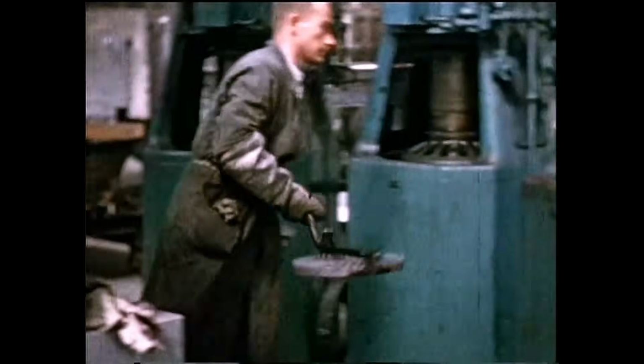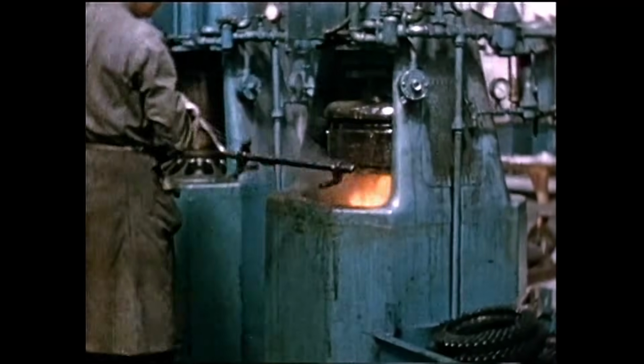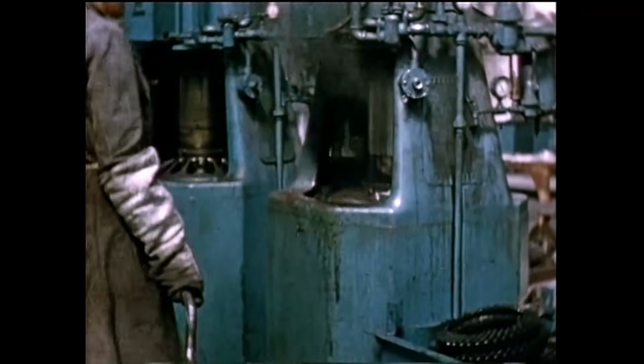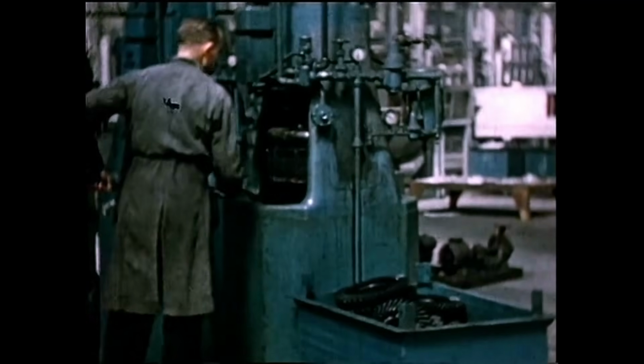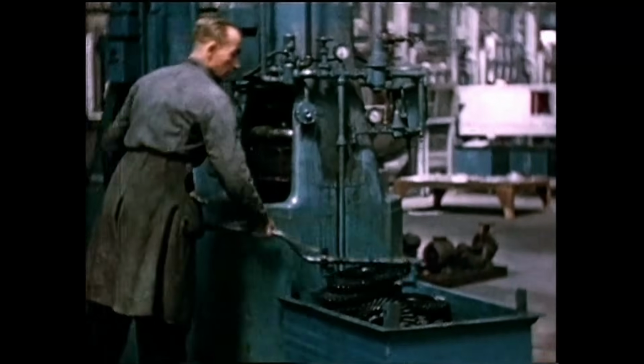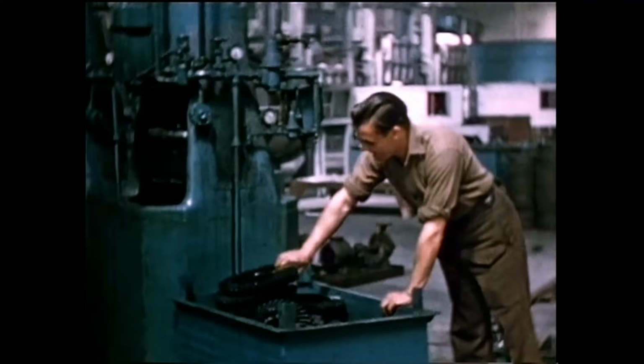Each wheel is placed in a Gleason press, where it is quenched in oil under a pressure of 50 pounds per square inch to prevent distortion during the cooling. After this, they're transferred to the final heat treatment, which consists of tempering at 200 degrees centigrade for a period of 1.5 hours.